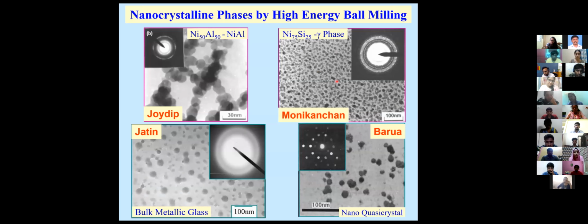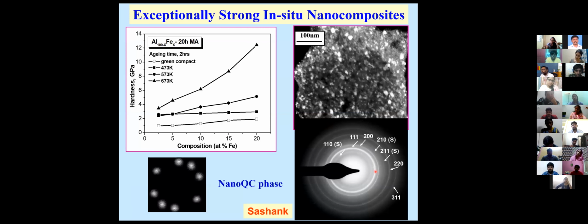And every particle, black dot that you see, okay, if you look at a scale here in an electron microscope, this will tell you that each of these particles is of the order of around 10 to 20 nanometers. And this kind of particles can be generated easily by this kind of technique. Almost everything can be broken. Even polymers, people have tried. They can break them into small nanoparticles by this kind of technique. And you have to find out what is the energy that I need to impart to convert a normal material into a nanomaterial. And once you get such a nanomaterial, there are many interesting properties.